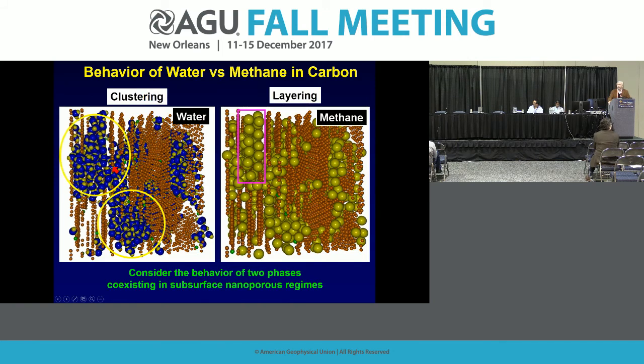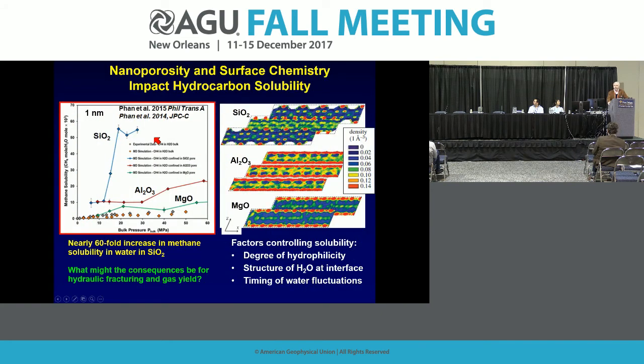So when we look at just comparing carbon and methane, the take-home message here is that for a hydrophobic surface like carbon, we see really different behavior, which will impact how we imagine transport and flow. For water and carbon, we see this clustering outcome in terms of how the water is contained within these pores at the nanoscale, compared to methane, which gives us a layering effect. So one can imagine how this might impact recovery of gas when you use water to frack a shale that contains organic carbon or carbon-rich pores, as we showed early on. So it's an interesting outcome, an interesting concern that we might have in terms of how to actually model this. Another interesting take-home message that I'd like you to leave with, that you may not be familiar with, is that the nanoscale solubility of these non-polar species actually increases.